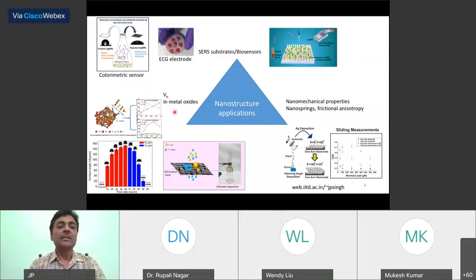Another area in which we are very active is the study of oxygen vacancies in metal oxides. For that, we try to fabricate different photocatalysts, and some of them we are using for CO2 adsorption mechanisms. Also their optical properties, and how they are affected by introducing a controlled amount of oxygen vacancies. That kind of study is also going on in my research group.